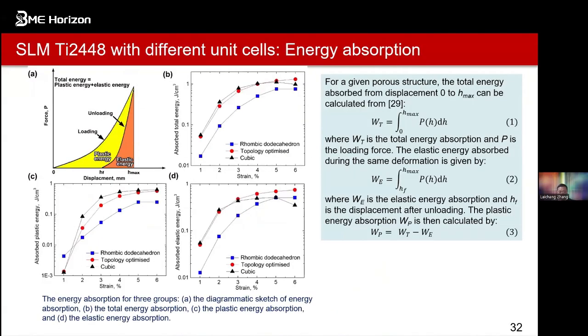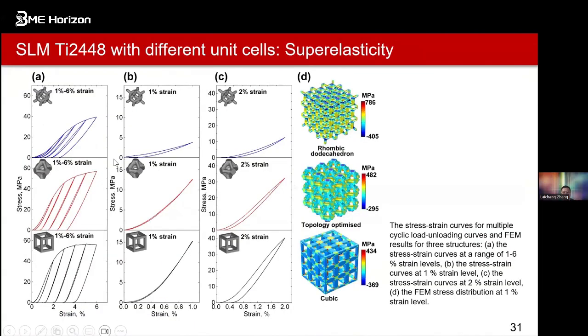We make a summary of this part. So that's why you can see the edge for these things. We can try to get this. You see the loading and unloading curve. So if this one is not fully recovered, it still has a gap. That means plastic deformation occurs, and the plastic energy is here, under the curve like this. But of course, under these things will be elastic energy as fully recovered. So from here, if we see it is fully recovered, that means no or limited plastic deformation has taken place. So from here we can see the elastic deformation.